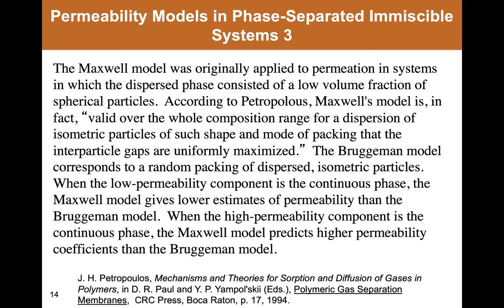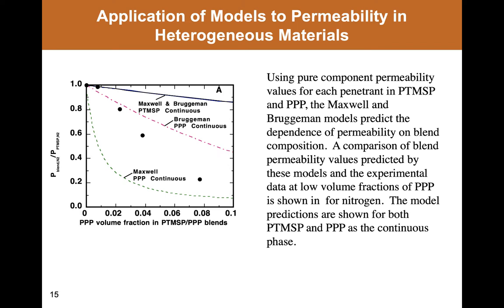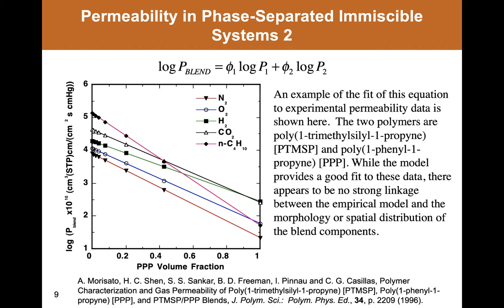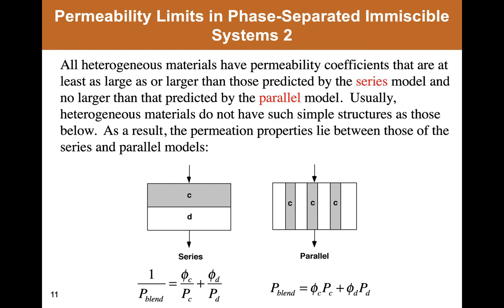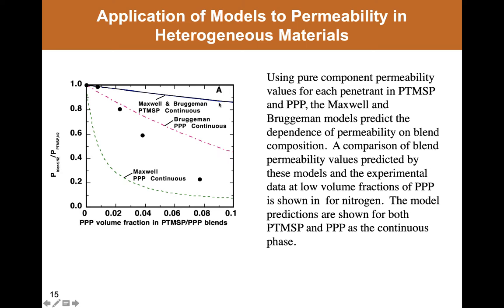To give you an idea of how these models apply to experimental data, this is showing the permeation properties of nitrogen through a blend of the two polymers we mentioned before that are phase separated, that is PTMSP and polyphenyl propyne. These are the ones that you'll remember fit this empirical model fine. But this doesn't give us any insight into the structurally heterogeneous nature of the blend. And so coming back and looking at the data more closely with models like the Maxwell and Bruggeman model will give us a different picture, or more complete picture, of the morphology of this phase-separated blend.